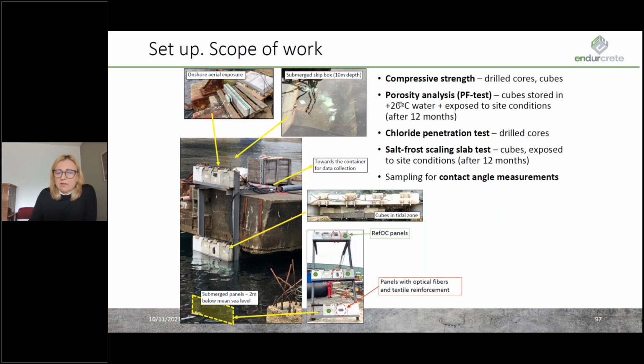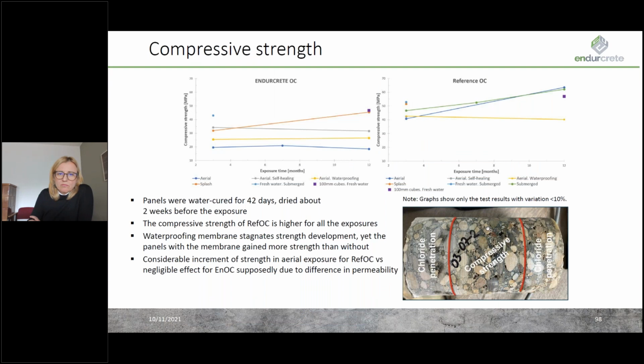The site was established in September 2020, and we have very fresh results after 12 months. The tests included compressive strength, porosity analysis, chloride penetration tests, salt frost scaling, and sampling for contact angle measurements. You can see some of the results here. The detailed results are presented in one of our last deliverables.